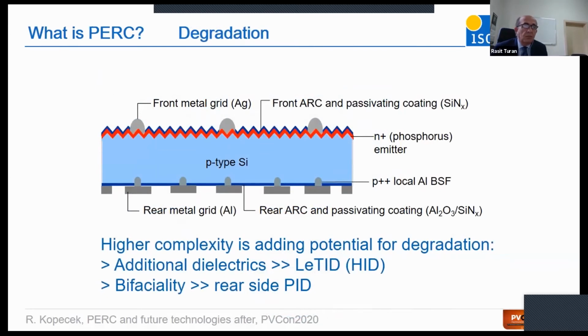So adding complexity to a system, of course, is also adding the possibility that some additional degradation can occur in the system. So when we are adding an additional dielectric, for example, the hydrogen from the dielectric could penetrate into the system, so we could have additional hydrogen-induced degradation. And if you are opening the rear side, then a probability for potential induced degradation is also there. But I believe that the large PERC producers, especially the tier 1 producers, they are understanding what they are doing, so there is not a big probability that the modules will degrade more in the field. But of course, you should test them.